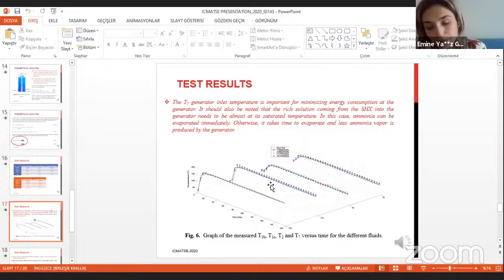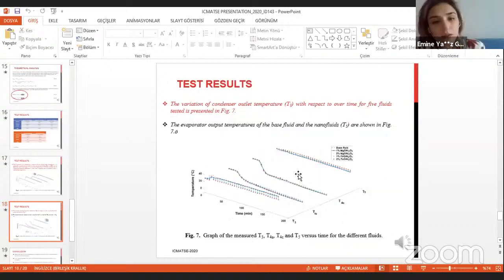And also we have temperature 1s and temperature 2. Especially, I would like to mention temperature 2, because temperature 2 is not stable, as you see. In base fluid, especially, there is a big difference. It is not stable. So it needs to be stable for the system.